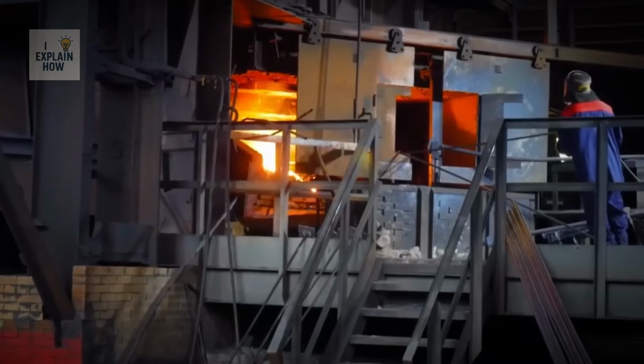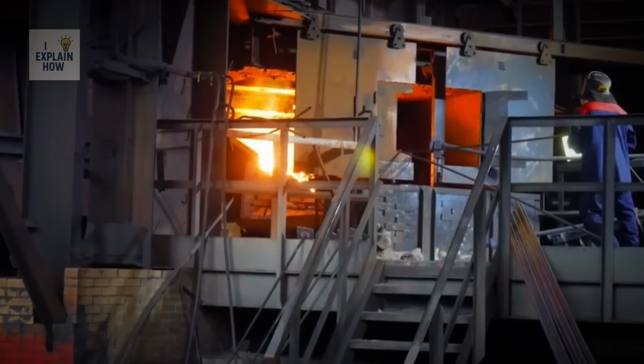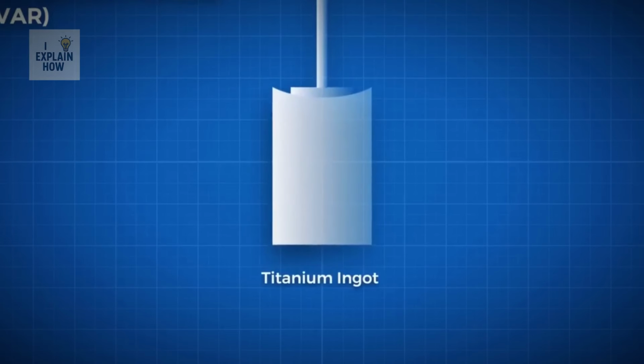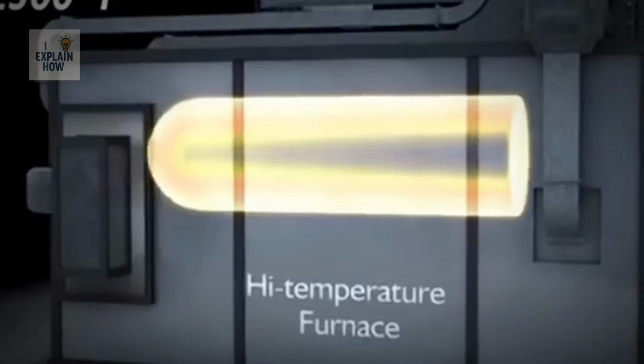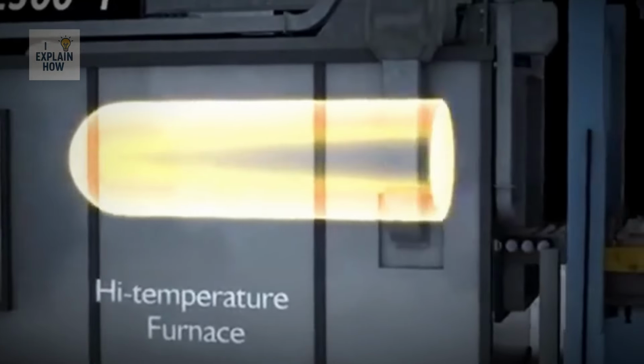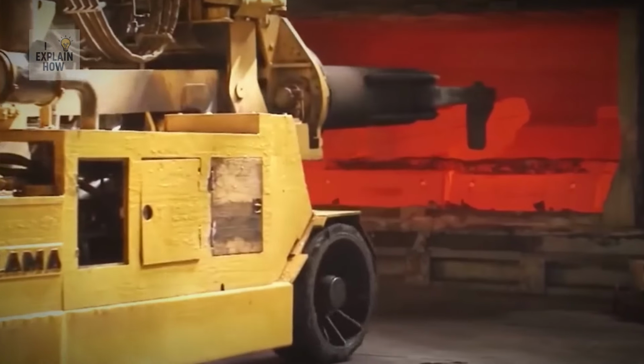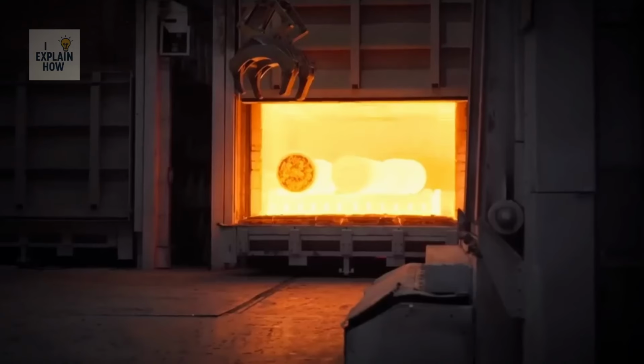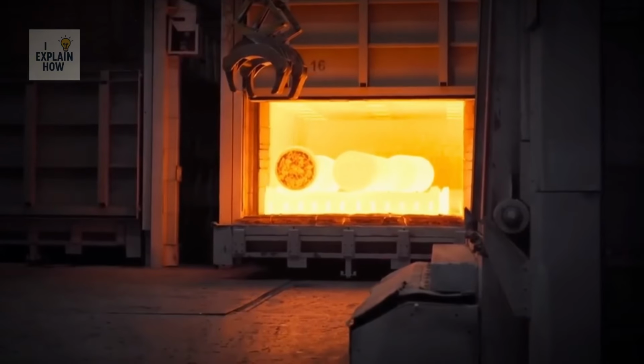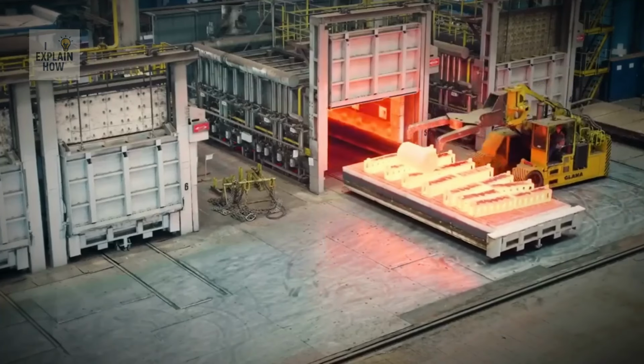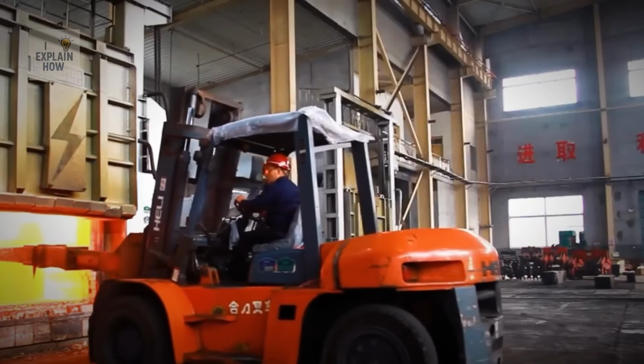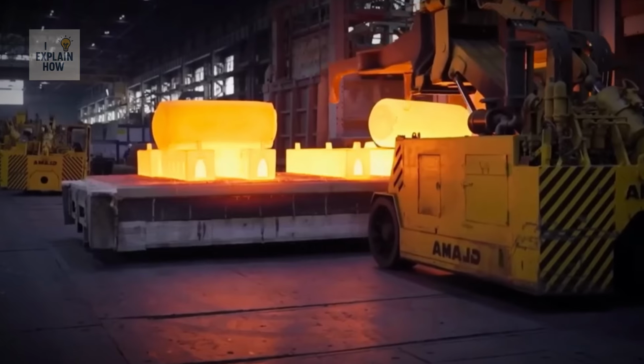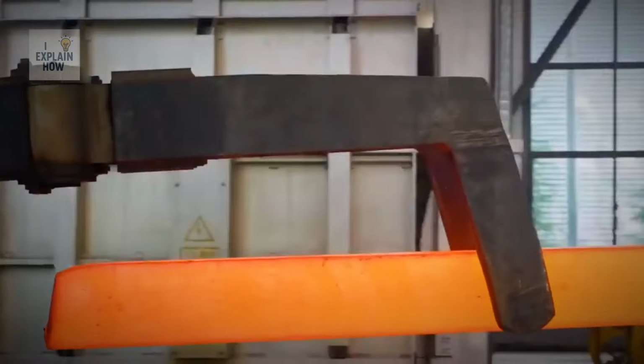All the air is extracted to create a near-total vacuum. Oxygen is titanium's worst enemy. At high temperatures, a single atom could make it brittle. Then the show begins. An electrical discharge of colossal intensity creates a luminous arc between the electrode and the base of the furnace. An artificial lightning bolt, brighter than the sun, generating thousands of degrees.